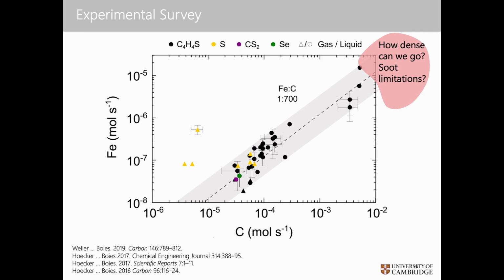When we look at the process as a whole, again, at a very macro level, and everyone who's published on this, and there's maybe 25, maybe 50 now, research groups throughout the world that are actively working in this process, and we put all of their recipes, for those that report them, onto a logarithmic scale, and one should always be suspicious of logarithmic scales, but nonetheless it does provide some guidance to us. We get pretty close clustering in the recipes in terms of carbon and iron that everyone feeds into this process. And so that is somehow fundamentally telling us that either A, people are just really influenced by the recipes others have done, which might be the case, but it probably is that there's enough motivation to study this now by enough different groups